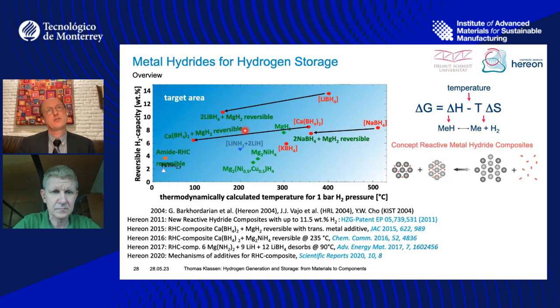Then you go to some other light metals like magnesium. Magnesium is a good candidate. Magnesium can store a lot of hydrogen, 7.6% by weight, and also has a high density for volumetric energy density. However, the reaction enthalpy of magnesium and hydrogen is much higher. So you only compensate for the enthalpy of bonding in this equation at a temperature of 300 degrees C. So this makes it okay if you combine it with a solid oxide fuel cell. But for a polymer fuel cell working at 80 degrees C, it's not feasible.